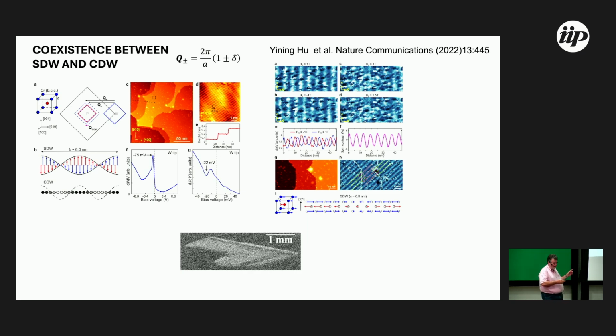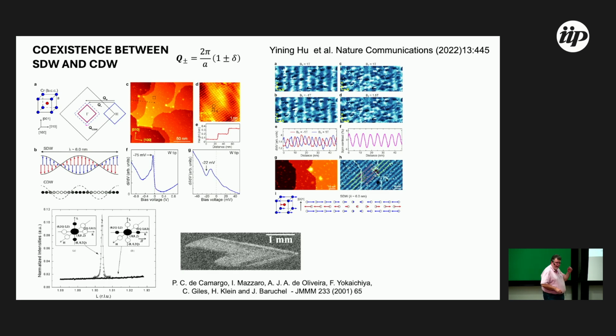This picture I measured many years ago in 2001 at SRF, using topography, magnetic X-ray topographies, observing the surface of the sample. One millimeter, it's a bulk sample, okay? In the L-shaped sample, we observed X-ray diffraction of the charge density wave. It is difficult to perform X-ray experiments on chromium because the signal associated with the spin density wave is very small. This experiment was performed at SRF, and the sample image is continuous because the charge density wave is continuous over the surface of the sample.